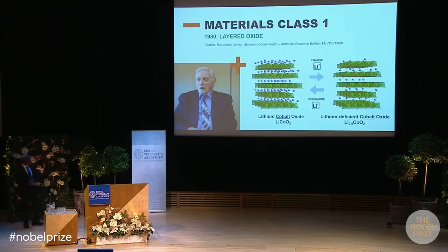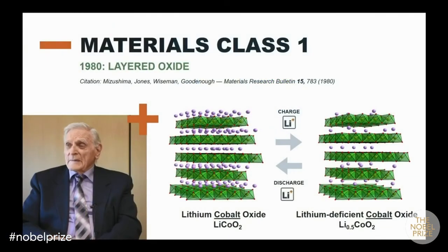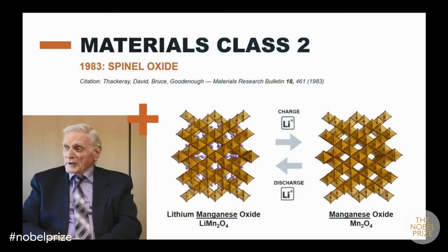I started with lithium cobalt oxide because it was a layered compound with ordering of the lithium and cobalt in alternate layers. And I investigated how much lithium I could take out of the lithium cobalt oxide before it changed its structure. And I found I could take out over half of the lithium without it changing its structure. And I could have, therefore, a reversible lithium insertion extraction oxide as against lithium insertion extraction sulfide to give me higher voltages.